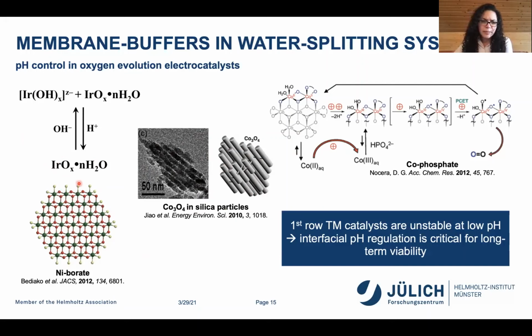And one of the key things in all of these materials is that pH gradients and proton control at the surface of the catalyst are very important, in particular for the first row transition metals, because these materials actually start dissolving or degrading at very low pHs. If we consider the fact that for every molecule of oxygen that we generate, we're generating 4 protons very close to the surface of the catalyst, then we really need to think about how we are going to ensure that these catalysts are stable for a long time.